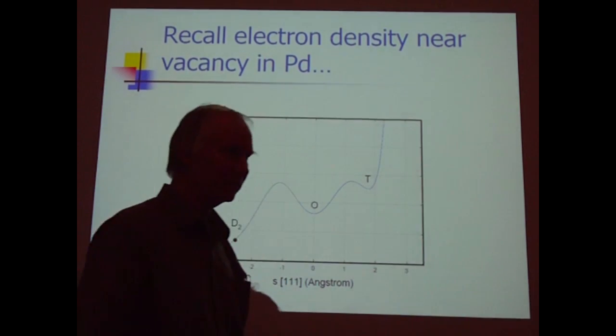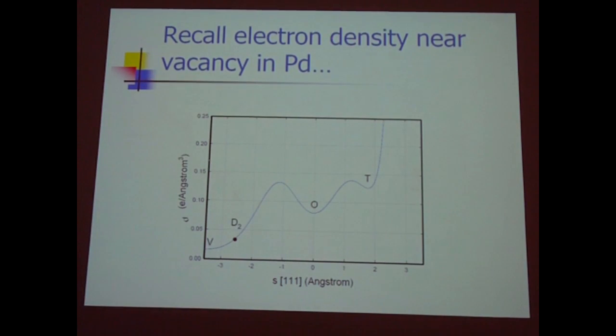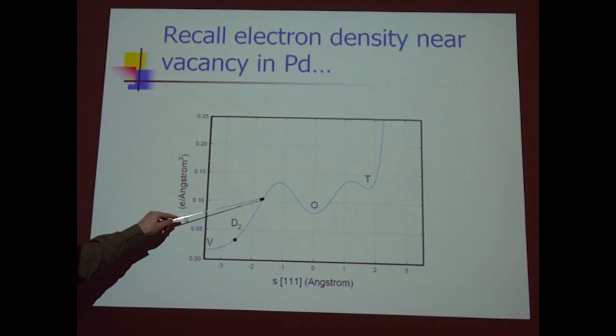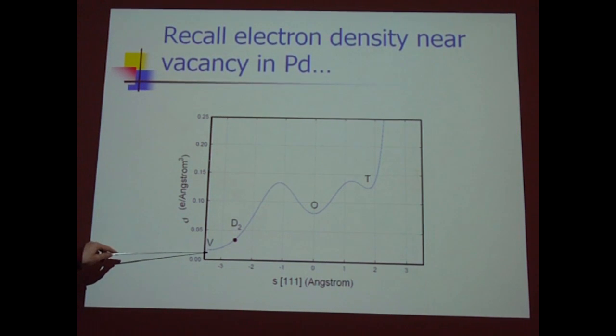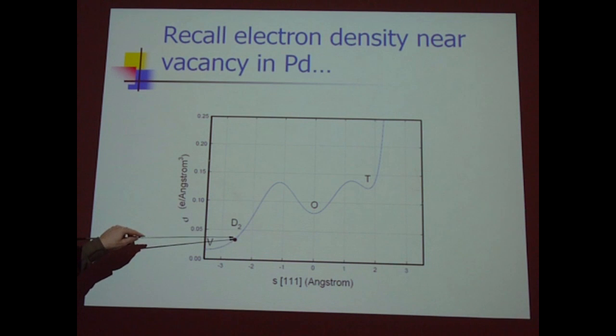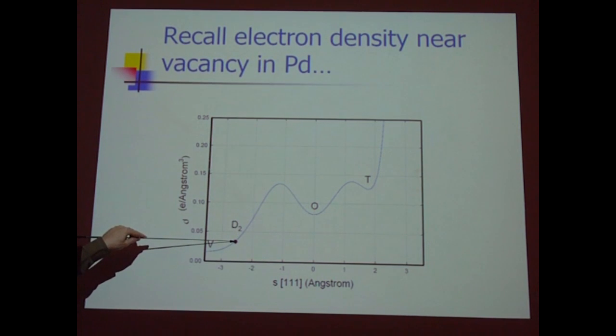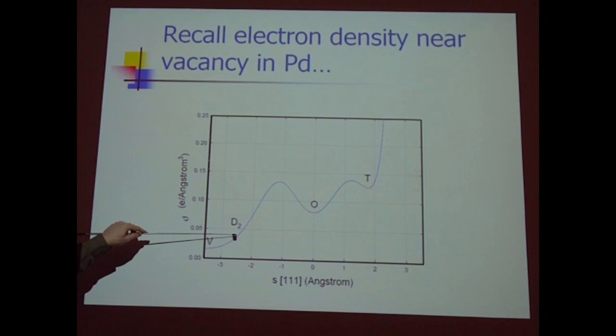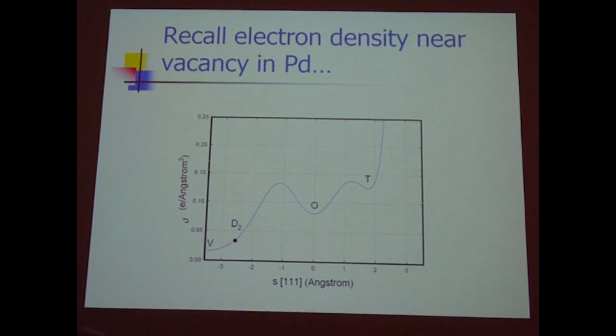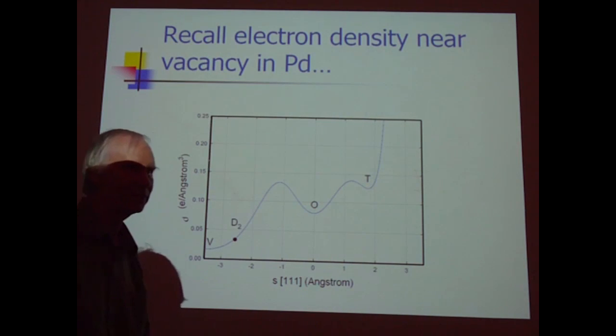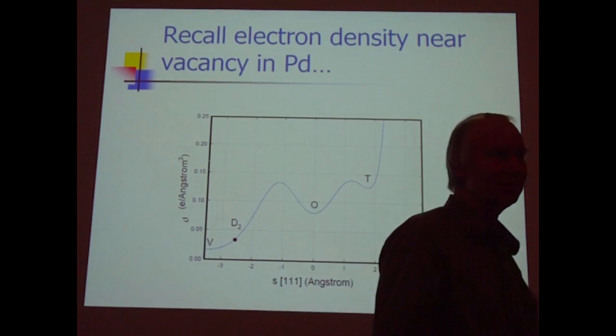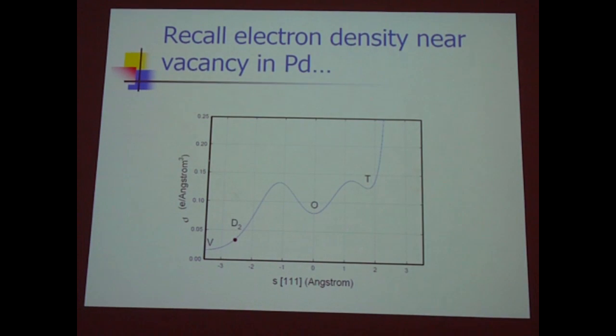And we argued that the nice thing about the vacancy is that around a vacancy, and this is palladium deuteride, you've got the possibility of getting the electron density to be sufficiently low to get a molecule. In nickel hydride, or in nickel around a vacancy, you also have electron density sufficiently low that you have the possibility of molecular H2 or HD formation or D2 formation. So that part of the problem is very similar.